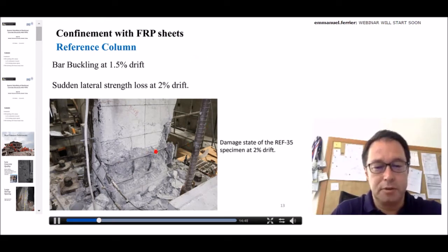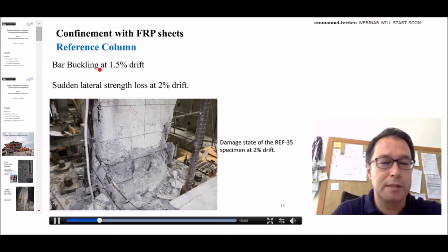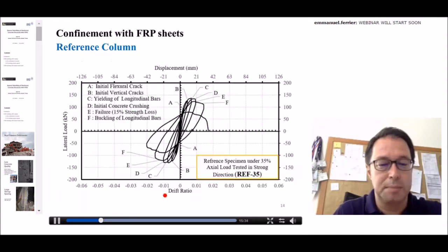So that's the result of the reference column. As you see, this is total failure. The specimen lost all axial load capacity, not only lateral load capacity. And this happened at around 2% lateral drift ratio. I should say that bar buckling was observed at around 1.5% lateral drift. Finally, at about 2% drift, the specimen lost all its axial load capacity, which means that the structure would collapse if this kind of drift is demanded from the structure during an earthquake. So apparently this damage mechanism tells us that if you confine this area, which we did for the next specimens, you could get much better seismic performance.